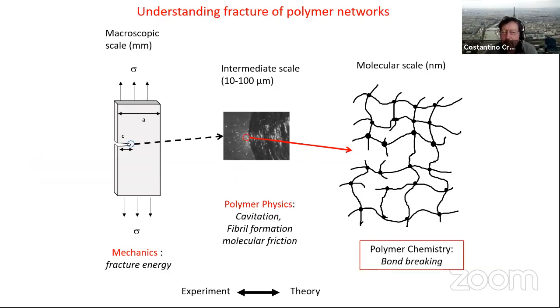Now coming back to fracture, from the point of view of a schematic picture of fracture, for me, there is on one end the mechanics, which tries to relate the macroscopic scale with local plasticity or deformation. And then you have an energy balance, you have stress fields, and this is really the realm of mechanics, very much macroscopic. At the intermediate scale, more microns, there may be heterogeneous deformation processes, which are localized plasticity for polymer glasses. But for soft material like elastomers, you can see things like filaments and cavitation, fibril formation. Those are typically at the micron length scale. They can be smaller, at the 10 or 100 nanometer, but often we still can see things optically.